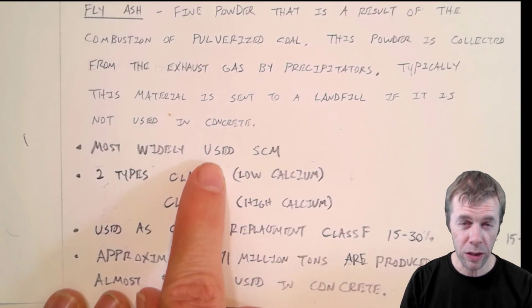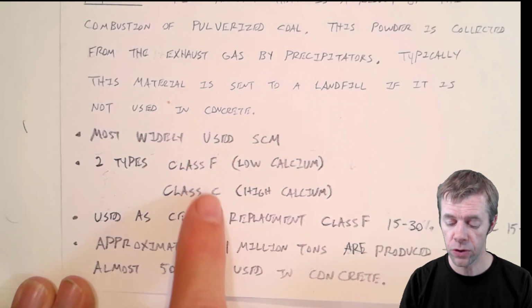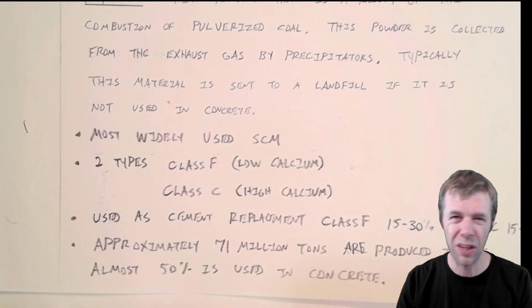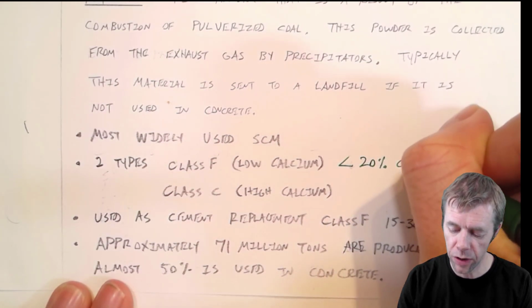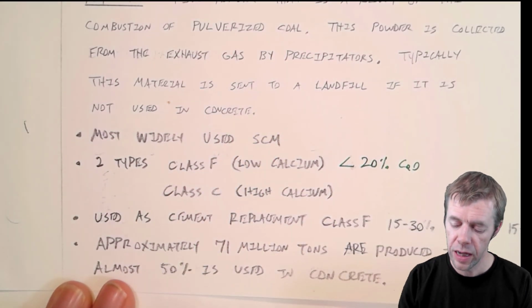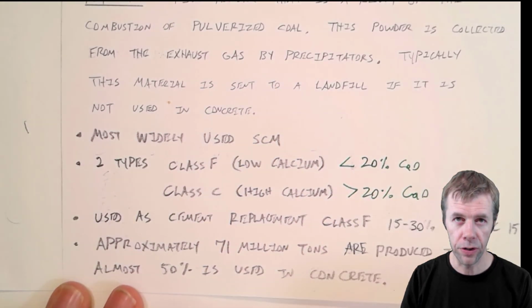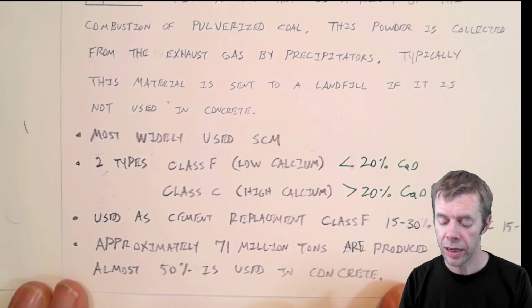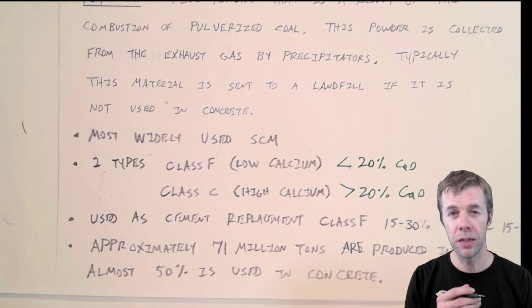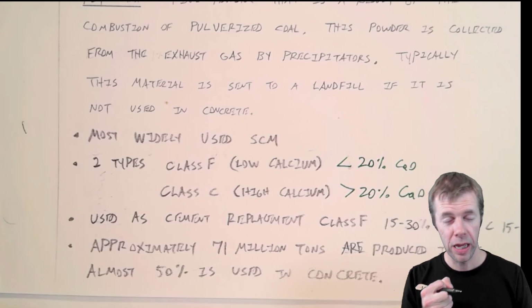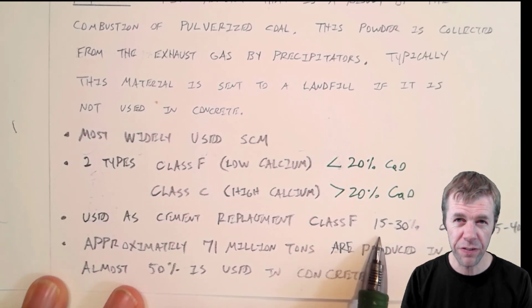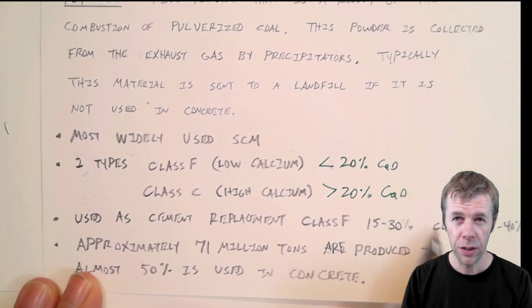This is by far the most widely used SCM. There are two types. There's class F, which is low calcium. You say, what's that mean? Well, if it has less than about 20% calcium oxide content, then it's a class F. And if you have greater than 20% calcium oxide content, it's considered a class C. And again, these things are used as cement replacement. You take out some of your Portland cement and you put this material in. For class F, sometimes you'll see it used between 15 and 30%. For class C, you'll see it used anywhere between 15 and 40%.